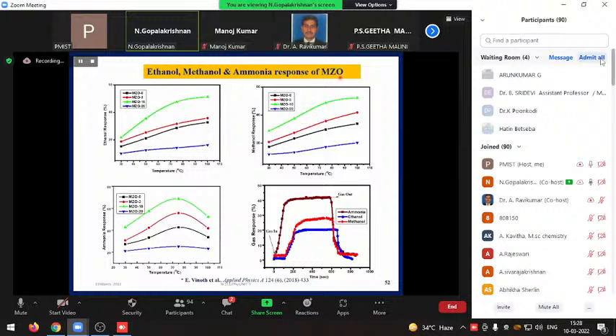So this is for the magnesium doped zinc oxide film. I don't want to repeat the same thing. We must see here, this black one is the pure one. In some cases, even with more dopant concentration, the response is reduced. So only for the optimum concentration is the gas sensing efficiency very high, in this case with magnesium.